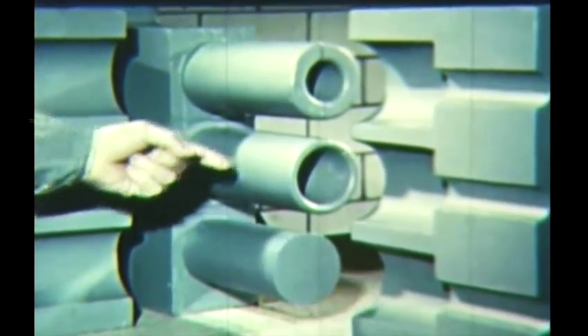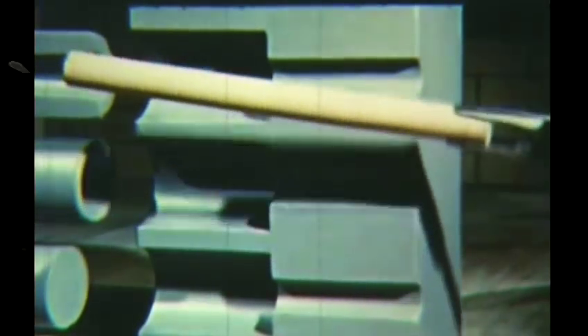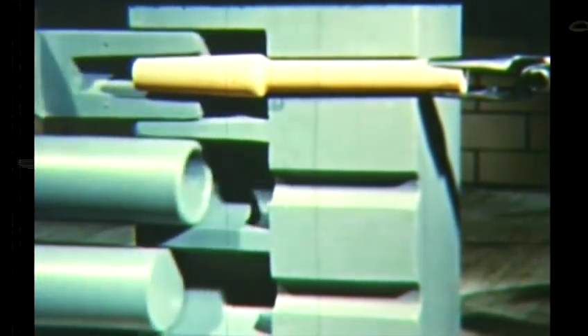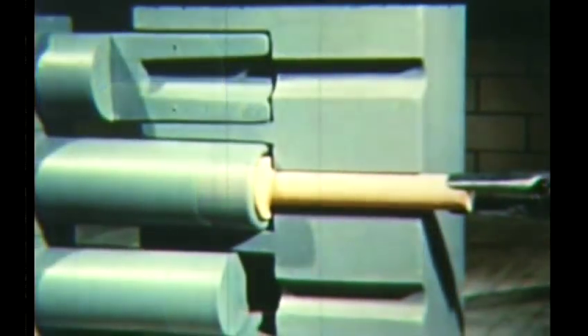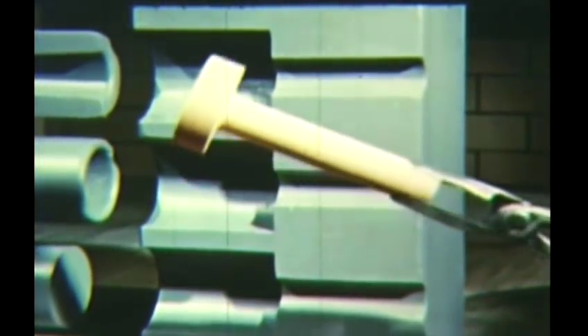The first two headers are hollow. The blank is a bar of forging steel heated to working temperature, inserted in the die cavity which then closes around it, gripping the bar tightly. The heading tool presses on the end of the bar with great force, shortening and expanding it to fill the hollow in the header, then withdraws. The piece is transferred to the second cavity, further shortening and expanding it. In the finishing cavity, a solid bar header expands the stock to the full diameter of the finishing cavity, and when it withdraws, the completed forging may be removed from the die.